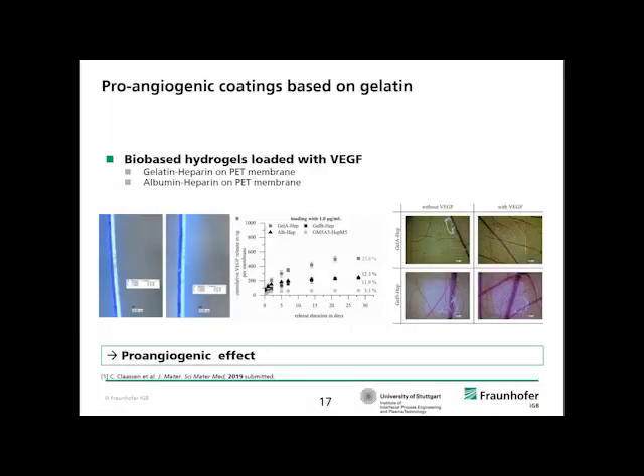Then another application for the gelatin-based materials, which is not really for an additive technique, is that we can use them for coatings. And here you see an example where we have a 10 micron coating, the dark blue coating on this thin PET membrane. And these coatings have been used as a storage for growth factors, in this case, the vascular endothelial growth factor. And you can see in this graph that from these thin layers, we can measure the release profiles of the growth factor.